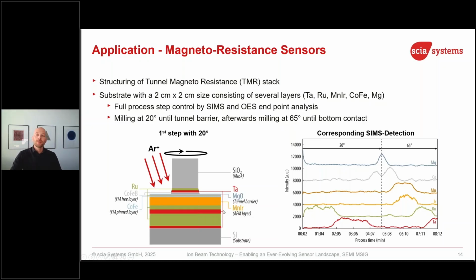In our system, we have a mass spectrometer connected. It's called a secondary ion mass spectrometer. It's an endpoint detection system. So we are able to detect the elements which are etched at each point in time. So during the etching time, we will see what is etched, and let's have a look at this magnesium signal here. So once we are within that tiny, thin, 1 nanometer thick magnesium oxide layer, we can do something. We can control the process.